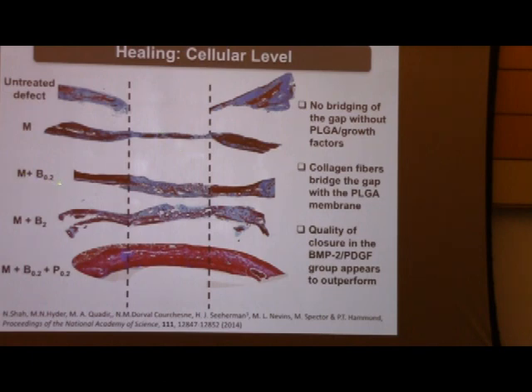If you introduce just a little bit, the 0.2 micrograms of BMP2, you get a lot of bone. So this just goes toward the idea that dose, when we're working with very controlled and localized release, really is not an issue. We can stay down at these very low levels. But we see that the bone is not very well formed or shaped. It looks, you know, for lack of a better word, lumpy. And when we introduce 2 micrograms, we increase the dose by a factor of 10, we get a bigger lump on the head of the rat. And you can see that there are some fairly large defects and irregularities along the surface of the bone.